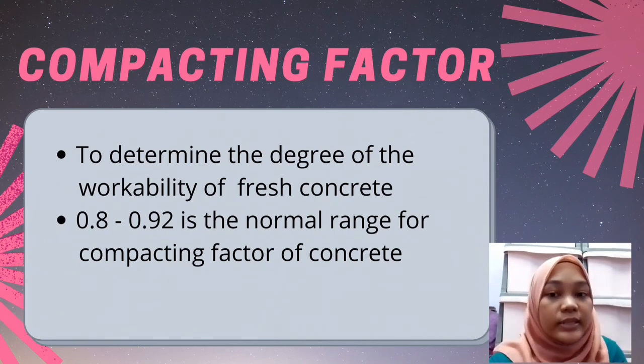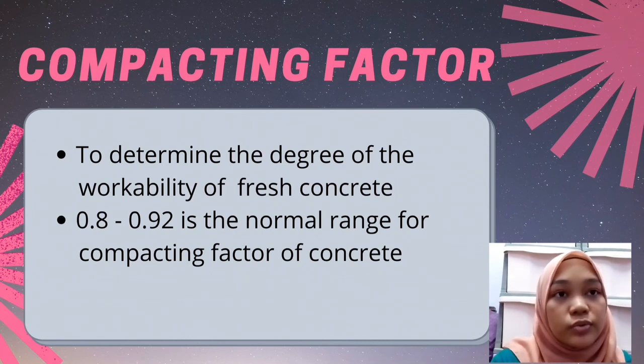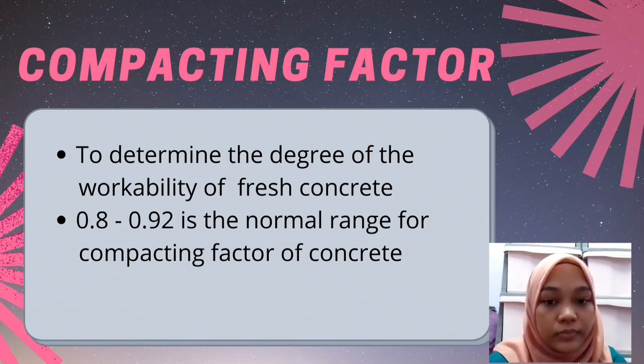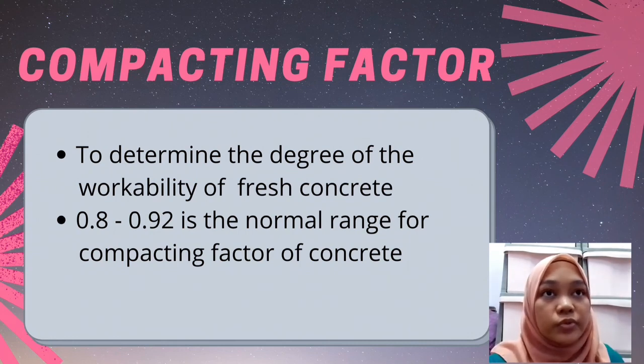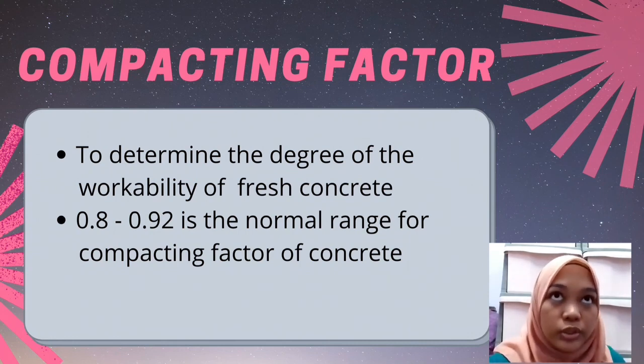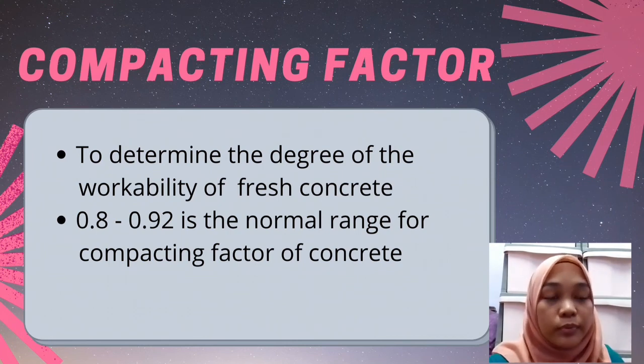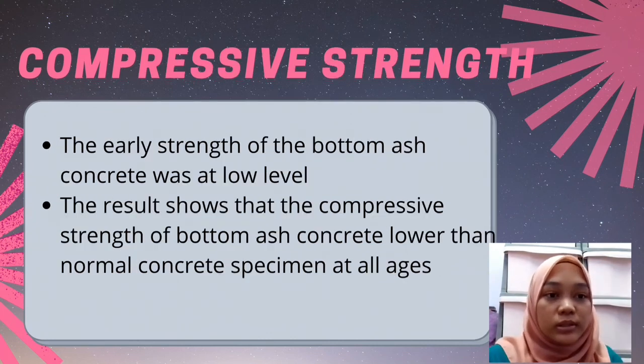For the compacting factor, as I said before, it is used to determine the degree of workability of the fresh concrete. Compaction factor can be defined as the ratio of the weight of partially compacted concrete to the weight of fully compacted concrete. The normal range for compacting factor should lie between 0.8 and 0.92. However, in these studies, the range of compacting factor is 0.65 to 0.75. It is due to the replacement of the fine aggregate with the coal bottom ash.